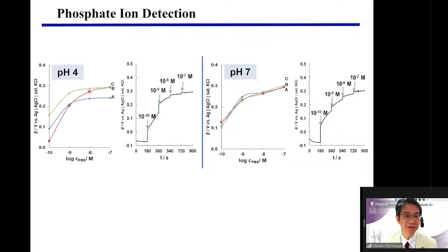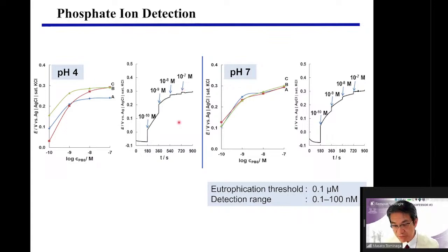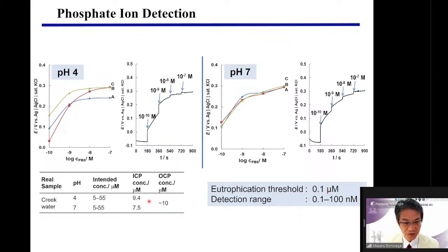Okay, this is the phosphate ion detection by using potentiometry. So this is the background potential. When we add a very small amount of phosphate ion, the potential changes to here. And then again, I add the phosphate ion, and the potential changes here. This behavior is observed in pH 4 and pH 7. This detection range is enough to detect the suitable concentration of phosphate ion. Also, I checked the phosphate ion concentration by the ICP method.